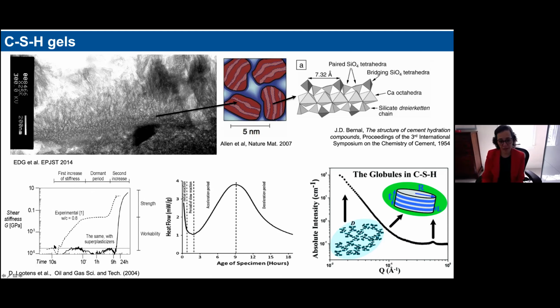And you can also see that the evolution of the mechanical strength, the shear stiffness here, actually has a first fast increase, then some sort of plateau, and then finally it increases to the strength that we need for making the building stand still. And the evolution of the mechanical strength is actually coupled to the precipitation process, which is basically related to this exothermic reaction underlying the production of calcium silicate hydrate.